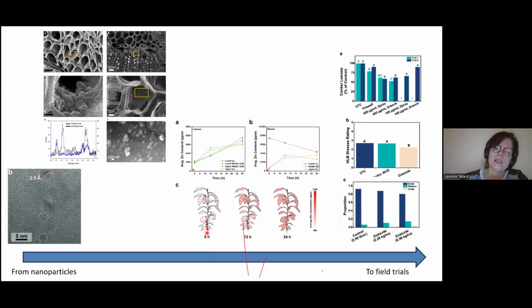So here we see that after 6 hours of treatment of the root, the concentration was highest in the stem. And after 12 hours, the concentration is highest in the stem, but it starts making it all the way to the top leaves. And after 24 hours, it kind of distributed all over the plants. That's important because at the time we didn't understand how the movement is happening.